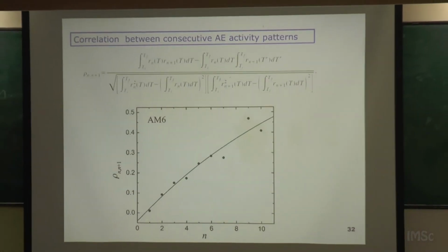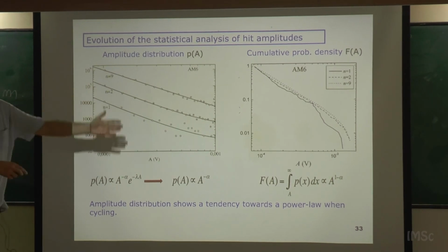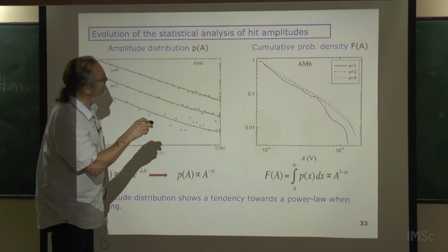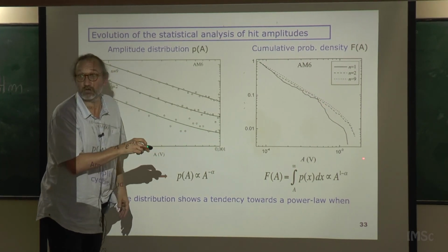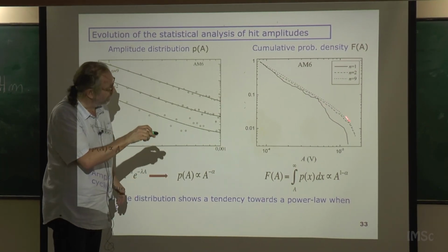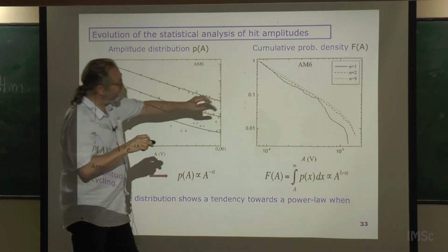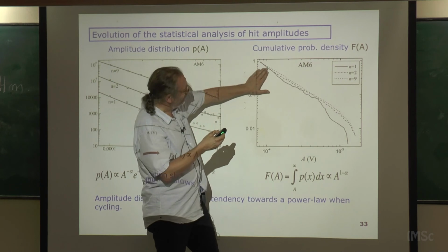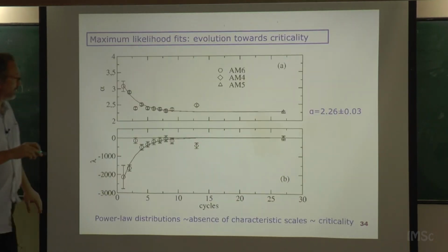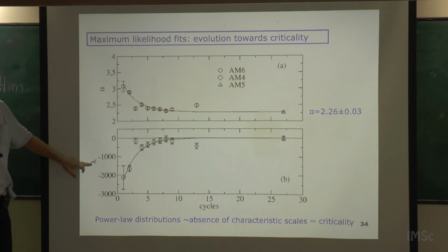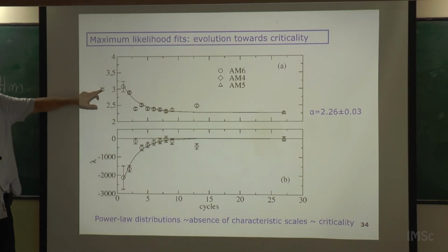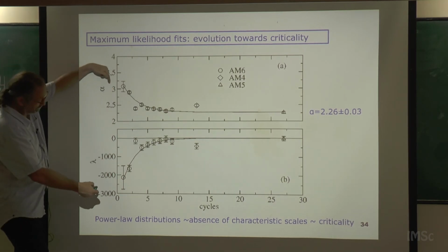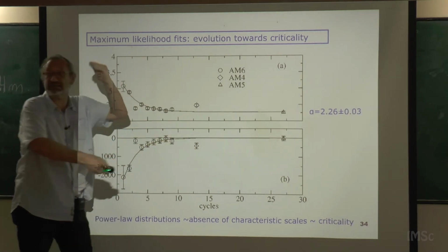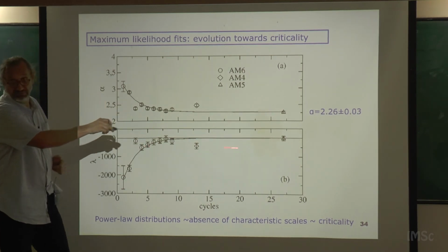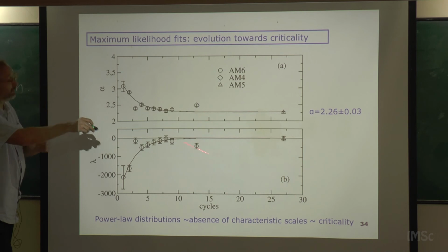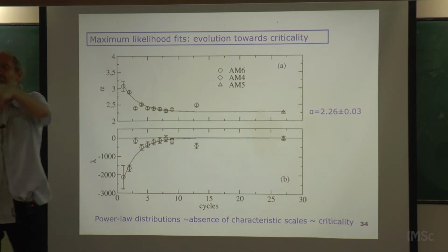Okay, so more or less this is what I show here. The first loop is this one, the distribution of avalanches, and when you increase the cycling, it gets more and more power law. This is not very nice, but when you feed this to a model that has a lambda correction and an exponent, you find that with the number of cycles these things change, and when you get the stable solution, lambda is 0, so you are critical, and the exponent has this value, which is the, let's say, universal one.